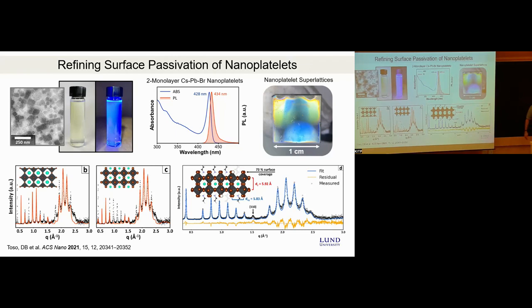So size dispersity from TEM, in our best samples, is an average size of 10 nanometers plus or minus 1 nanometer. That's what we get from TEM. So that's on the order of your ligand shell thickness. And so I'm wondering, what role does that play in terms of this densification?